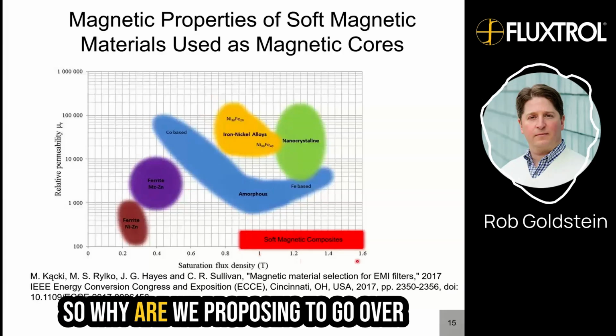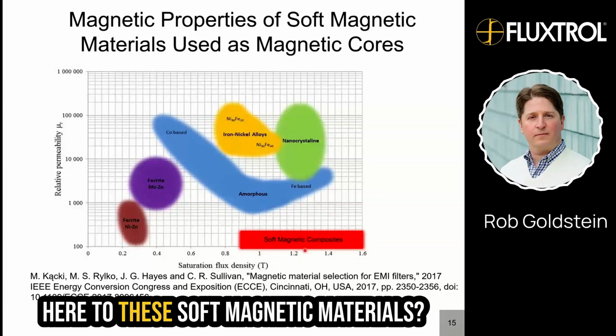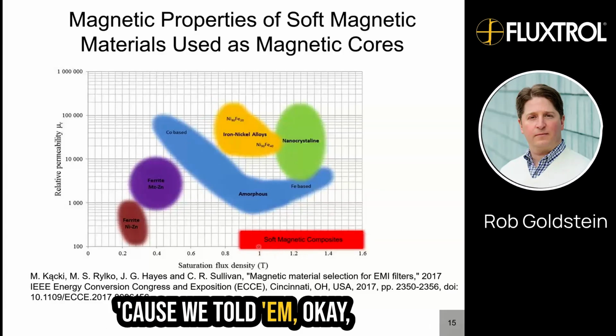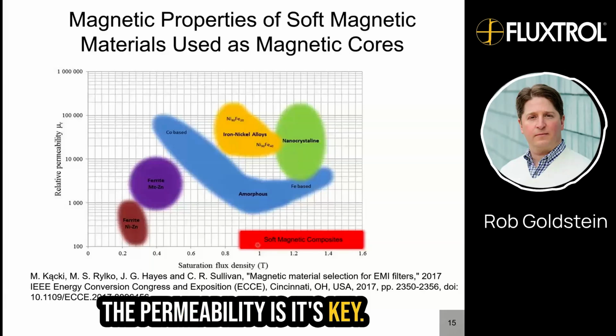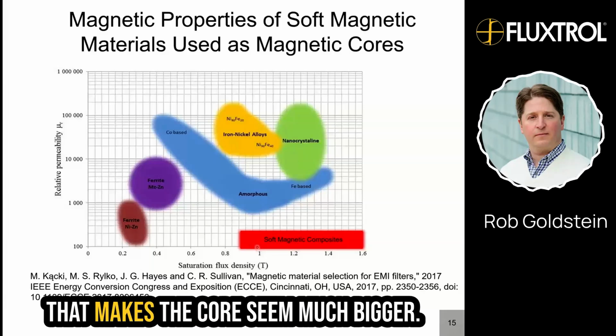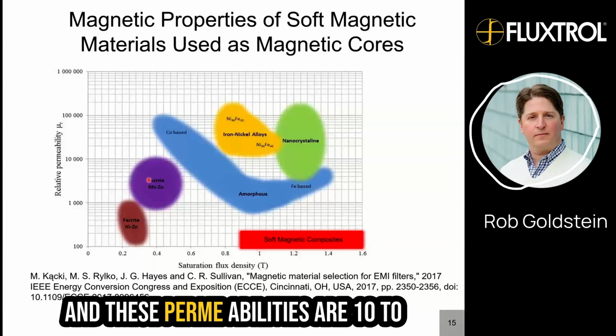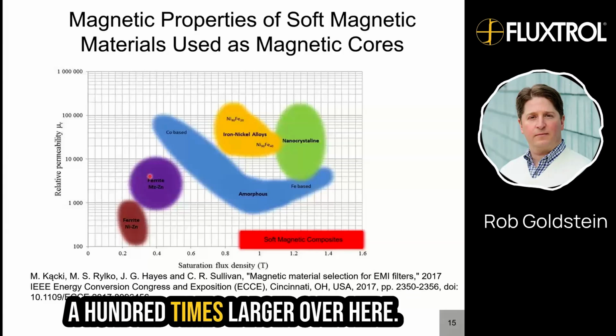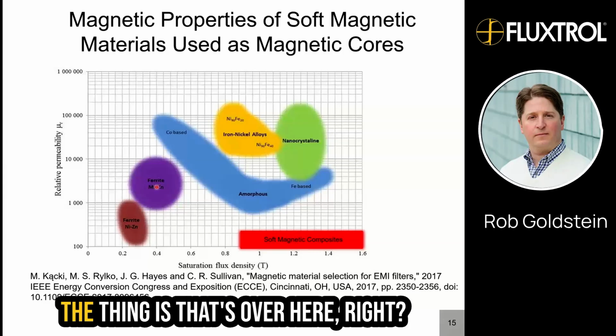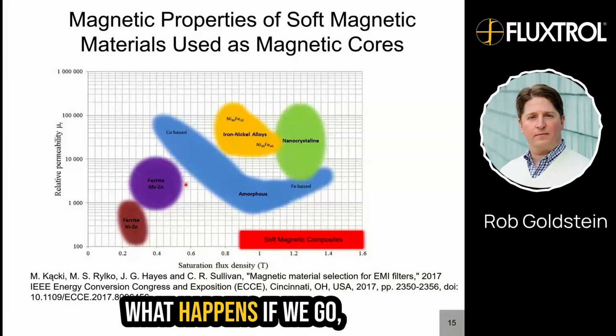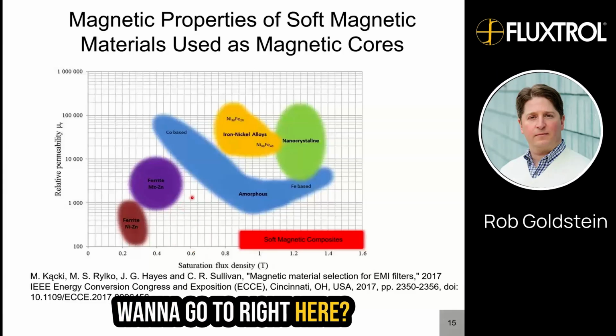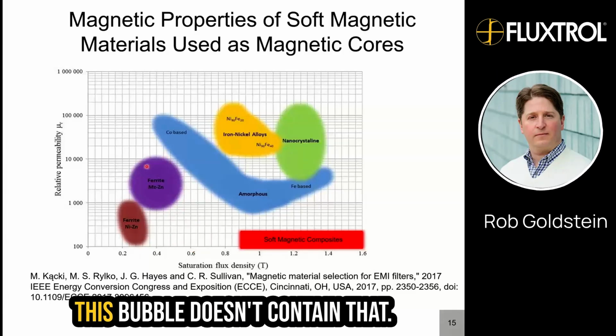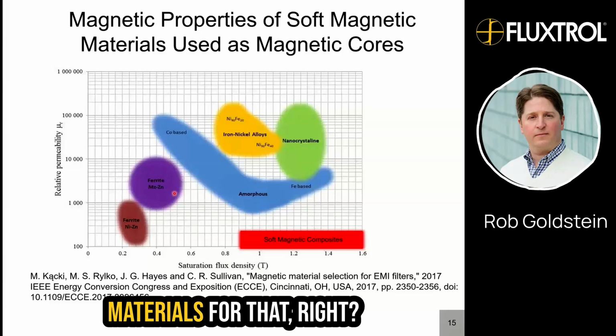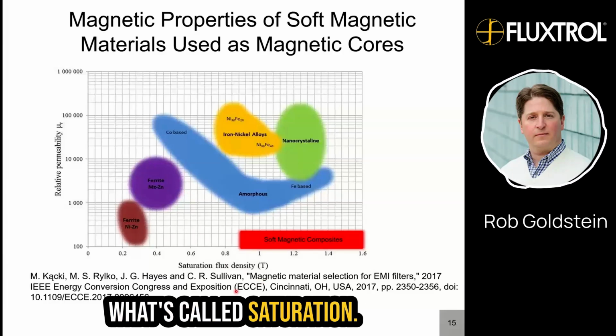So why are we proposing to go over here to these soft magnetic materials? Because we told them the permeability is key. Higher is better, right? That makes the core seem much bigger, and these permeabilities are 10 to 100 times larger over here. The thing is, that's over here. What happens if we want to go to right here? This bubble doesn't contain that because there really aren't materials for that. And that's when we get what's called saturation.